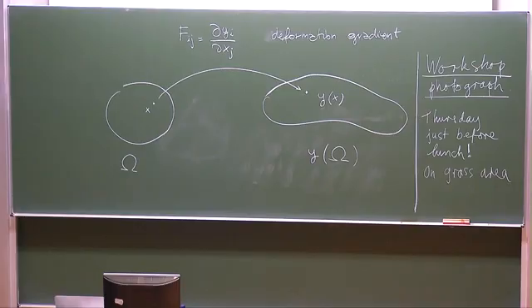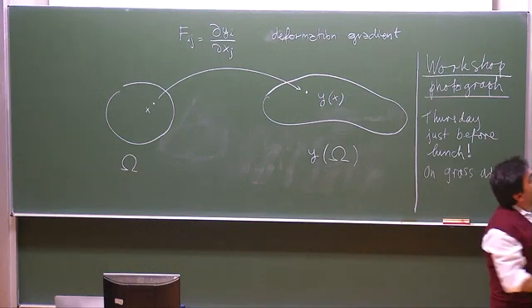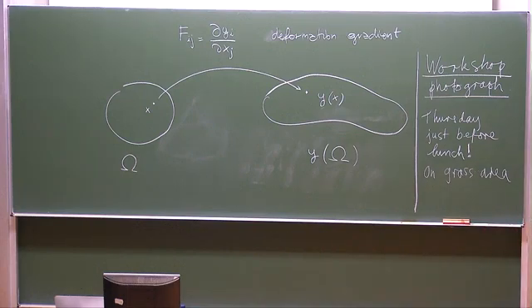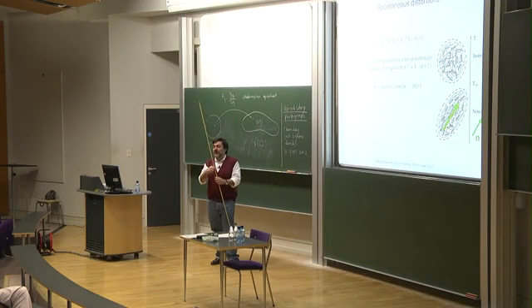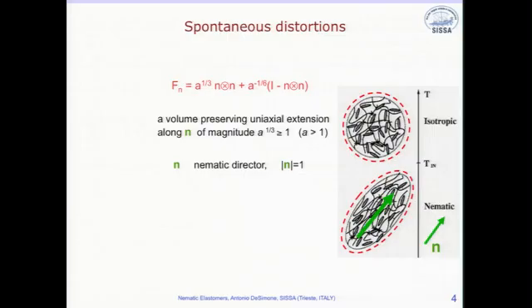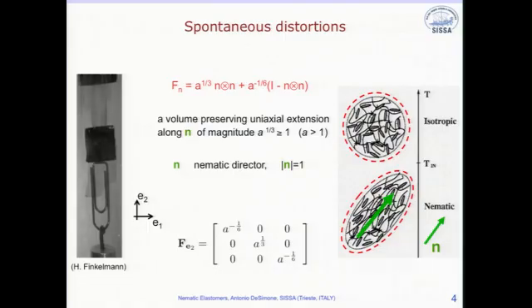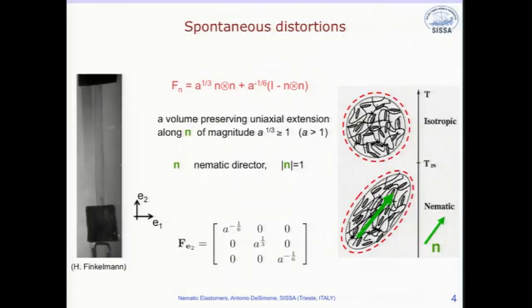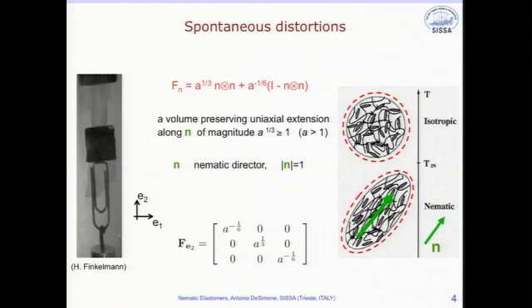This number bigger than 1 means elongation along n. These are the two directions. This is n tensor n. And this is the stuff that comes from the volume conservation. So all the perpendicular directions to n contract by a number such that the determinant of this should be 1. Okay? In concrete, so in this experiment, this is the deformation. So it's a spontaneous distortion accompanied to the vertical orientation of the director. This is the matrix. This is how much you stretch along the direction of alignment. This is the amount you contract in all other directions. Okay. So this is bit number 1.